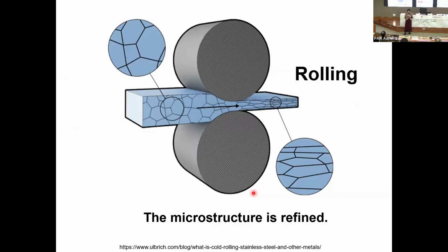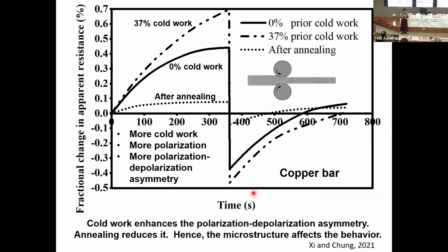I already mentioned that rolling can cause the microstructure to be refined. And so we looked at metal, copper, and this asymmetry gets more if you cold roll, 37% versus 0%. And if you anneal it afterward, you just kill that thing. And so it becomes very low in polarization. That is, the curve is kind of low, and also it becomes symmetric. So cold work enhances this asymmetry, and annealing reduces it. And so the microstructure strongly affects the behavior.